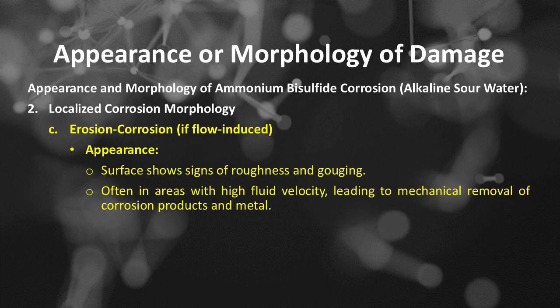Number C of the localized corrosion morphology is erosion corrosion. If flow-induced, the appearance of erosion corrosion includes a surface showing signs of roughness and gouging, often in areas with high fluid velocity, leading to mechanical removal of corrosion products and metal.